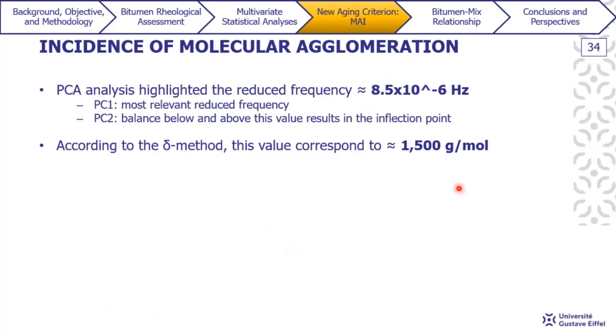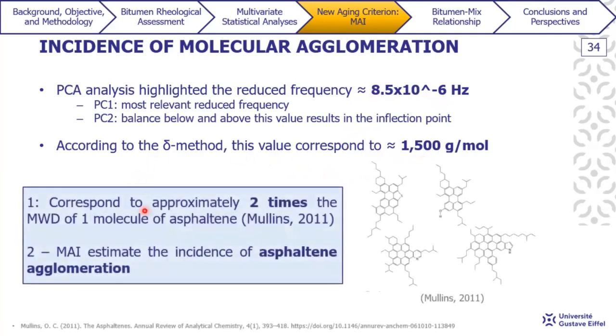When we go back to the findings from the PCA analysis, the PCA highlighted the reduced frequency of 8.5 times 10 to the power of minus 6 hertz to be the most relevant reduced frequency for PC1. And PC2 represented the balance below and above this value, which resulted in the inflection point that we observed, even though the contribution of PC2 is very low, around 3%. According to the delta method, this value corresponds to 1,500 grams per mole, which according to the literature corresponds to 2 times the molecular weight of a single molecule of asphaltenes, according to Mullins. So in this case, MAI seems to estimate the incidence of asphaltene agglomerations.